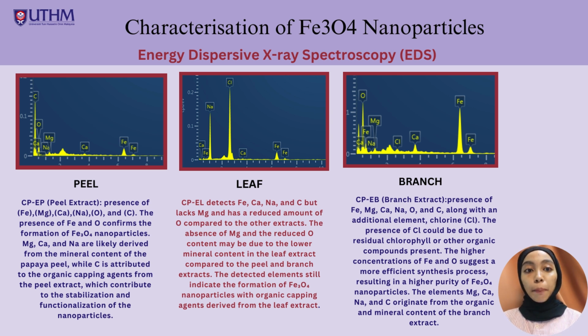So the second sample, which is leaf, all the elements are present, but the absence of magnesium and the reduced oxygen content may be due to the lower mineral content in the leaf extract compared to the peel and branch extract. The detected elements still indicate the formation of iron oxide. And lastly is branch.